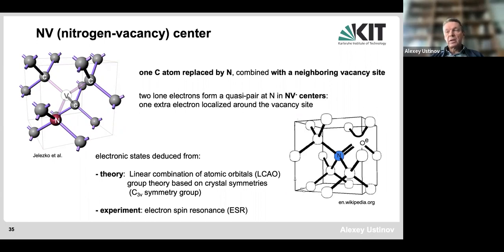Or you could, for example, put the diamond piece into a nuclear reactor and then add some nitrogen atmosphere, and then high energy particles will destroy some of the sites in diamond, and then the sites can be occupied by nitrogen atoms. So imagine that you have a regular lattice from which you took away 2 neighboring carbon atoms. And then instead of placing back 2 atoms, you placed back only 1 atom, which is a nitrogen atom, which is slightly larger than carbon, and therefore the neighboring place near the nitrogen stays unoccupied. So there will be basically a vacancy situation.